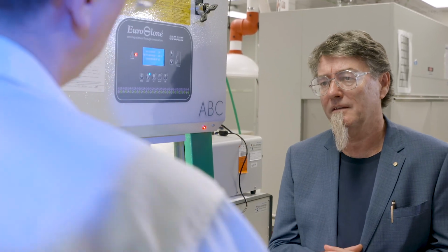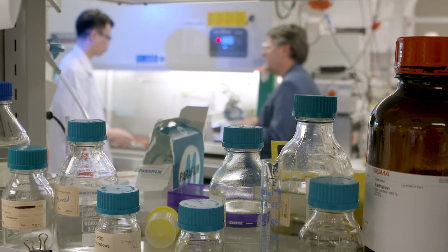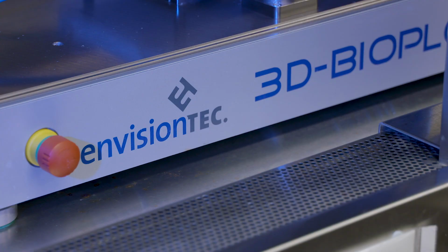And what types of structures have been printed using the GeSiM? So for GeSiM, we've obviously printed simple structures such as the cubes, but we also use this for coaxial printing. It has a coaxial head that some of the students are working on drug delivery patches, and also, for example, the melt electrowriting, it would be really thin scaffolds that has a lot of flexibility, so kind of also like a patch. And the coaxial head is around the extrusion printing, or both? It's for extrusion only. So it has a particular head where we can put two materials, one in between the other, and then you can load your core with drugs or other growth factors.